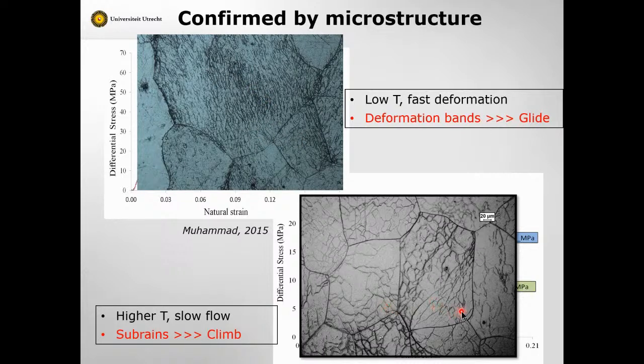Much slower deformation, for example, at rates when you're thinking of strains occurring on tens, hundreds of thousands of years, or geological timescales, higher temperatures, you get this totally different internal structure within the grains. Look at the difference. Here you see these little cells or subgrains developed. This is absolutely characteristic of dislocation climb. So it's completely consistent with our mechanical data.